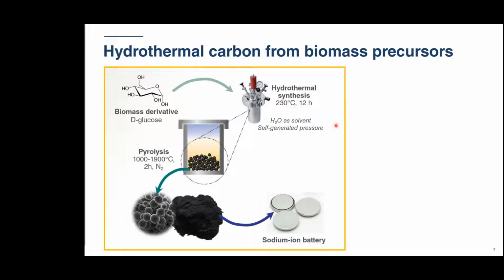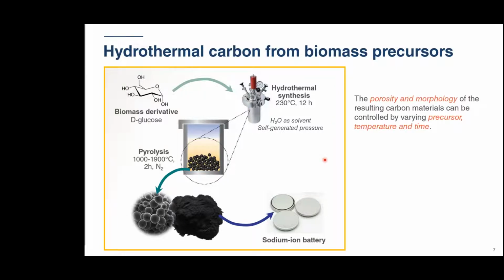Okay, so just to continue then, we can also tune the carbon surface using this additional thermal treatment. And so we can tune the surface chemistry and electronic properties. So we derive these really nice spherical particles from our synthesis method, and we can finely tune from the microstructure all the way down to the nanostructure, just purely by controlling the pyrolysis temperature. So it's really very simple. And then tuning the structure really is the key to optimizing the sodium-ion storage. So there are various different structural features in the carbon that can store sodium, and we can exert control over the pore size, the interlayer spacing, and the level of defects on the surface. And we see when we build the sodium-ion battery that we can really change.